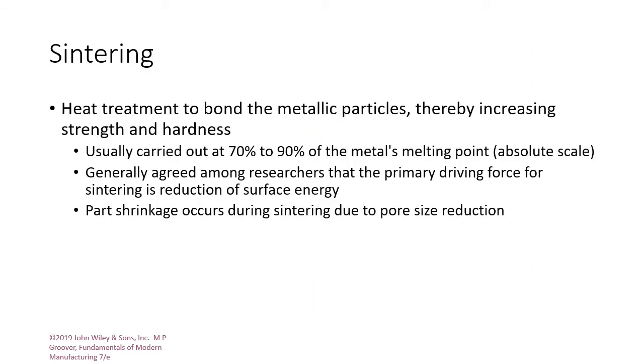The third and last step is the sintering. After pressing, the green compact lacks strength and hardness, so we need to improve the strength and hardness of the product by heat treatment, which bonds the metallic particles. Usually, we reach a temperature of 70 to 90% of the metal's melting point, and it is generally agreed among researchers that the primary driving force for sintering is reduction of surface energy. The part shrinkage occurs during the sintering due to pore size reduction.